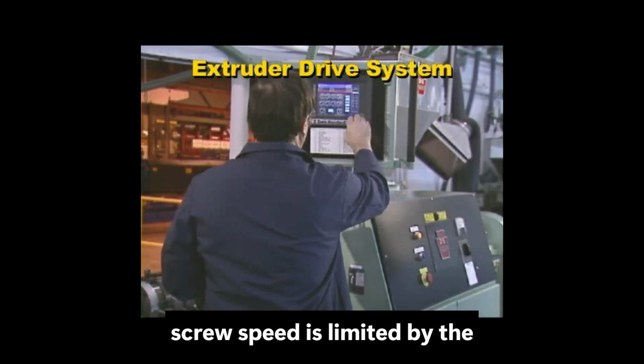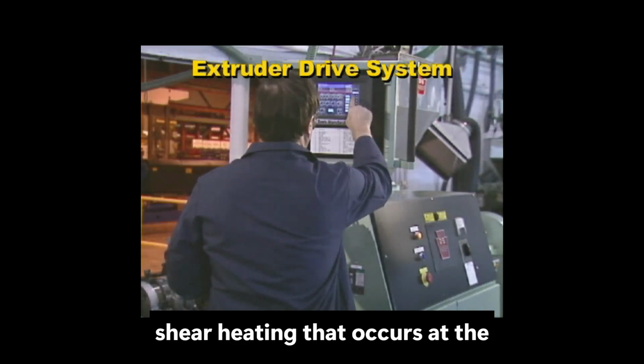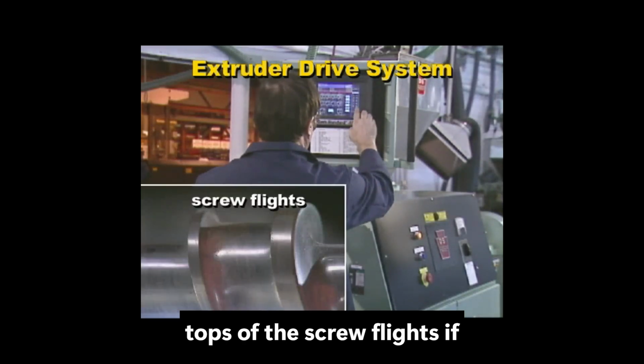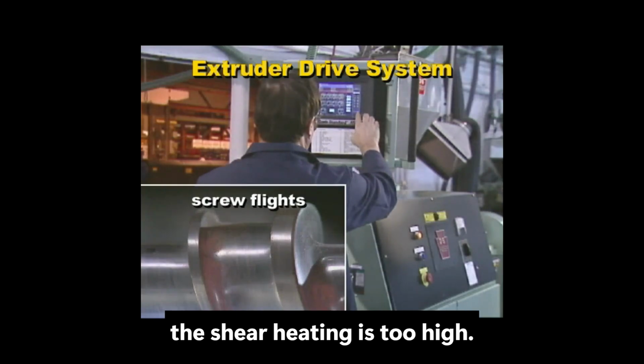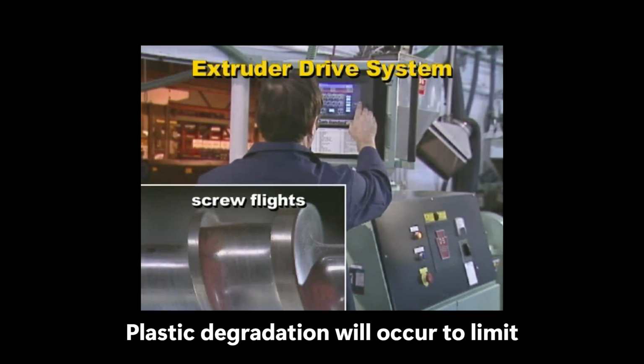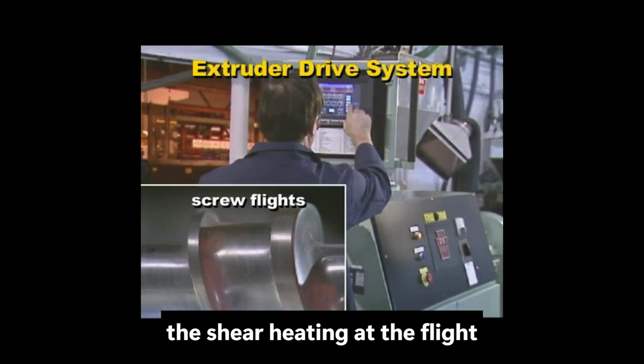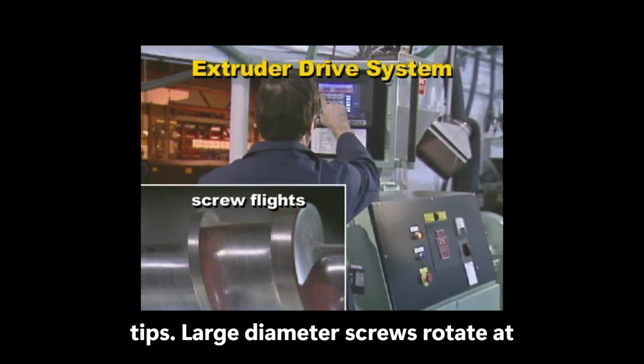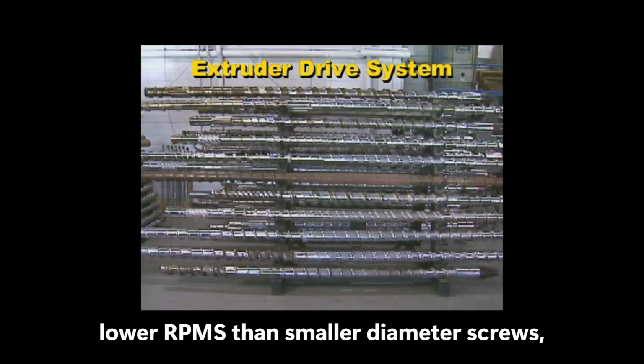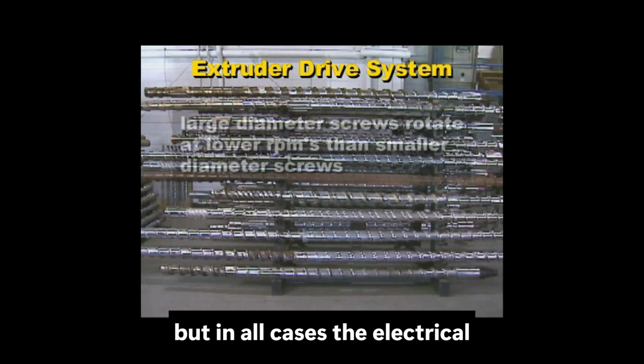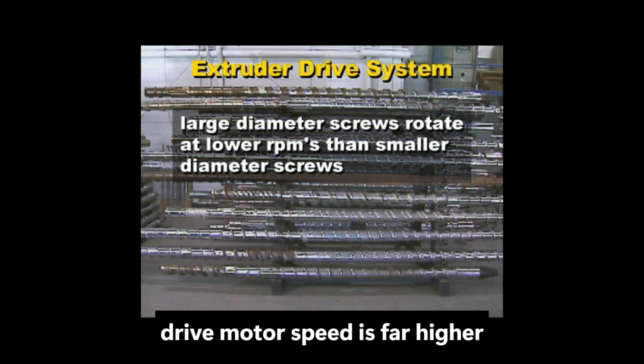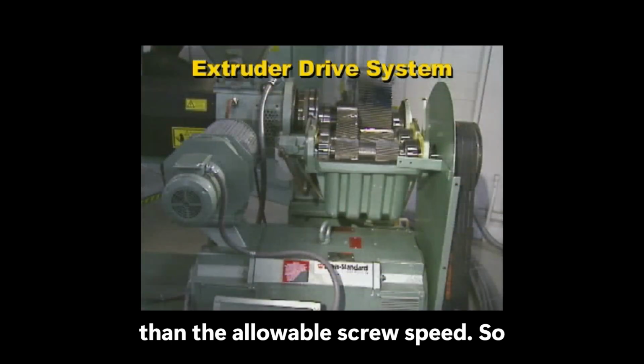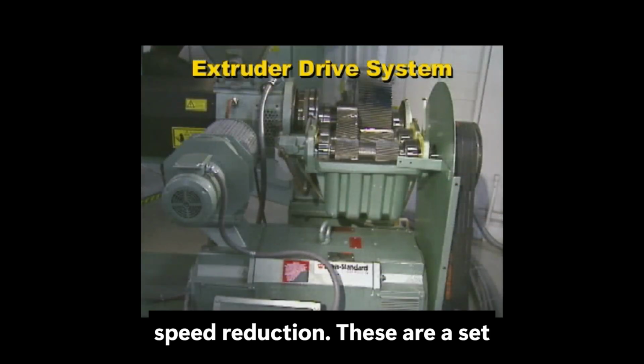The maximum screw speed is limited by the shear heating that occurs at the tops of the screw flights. If the shear heating is too high, plastic degradation will occur. To limit the shear heating at the flight tips, large diameter screws rotate at lower RPMs than smaller diameter screws. But in all cases, the electrical drive motor speed is far higher than the allowable screw speed, so speed reduction is needed.